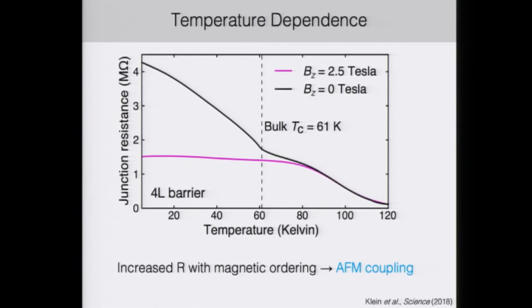So first, let's take a look at what happens as we cool down one of these devices. As we cool down in zero field, we see that the junction resistance has a kink right around the Curie temperature of the bulk, which is consistent with magnetic ordering in the barrier. Furthermore, we see that the resistance increases as we cool down below this temperature, and this increased resistance with magnetic